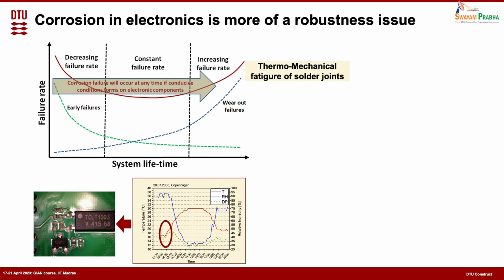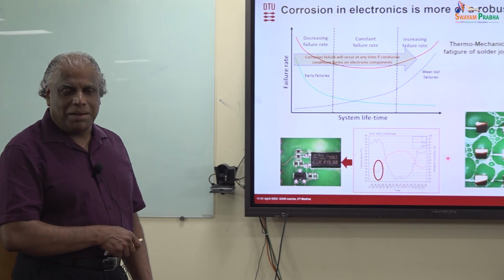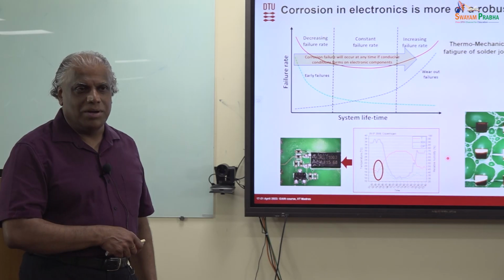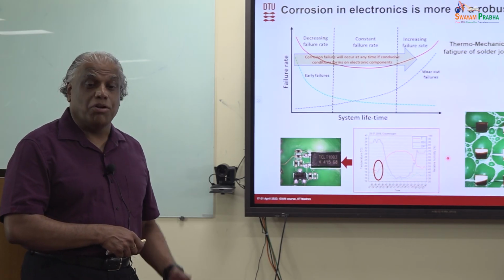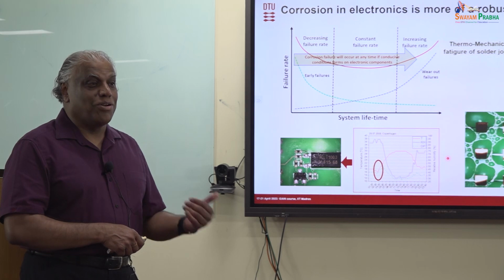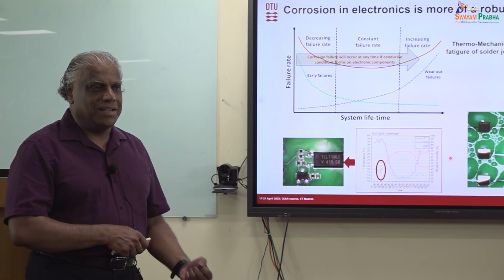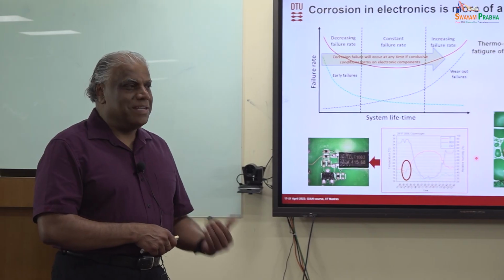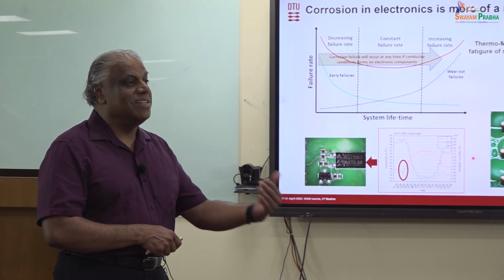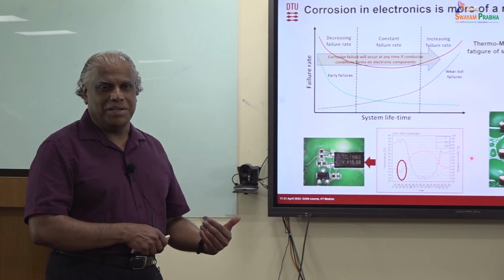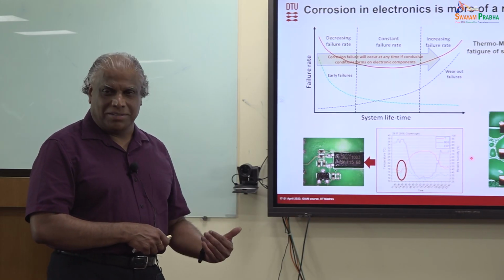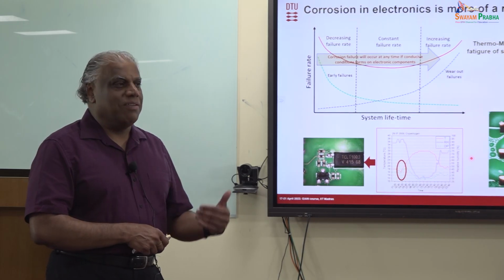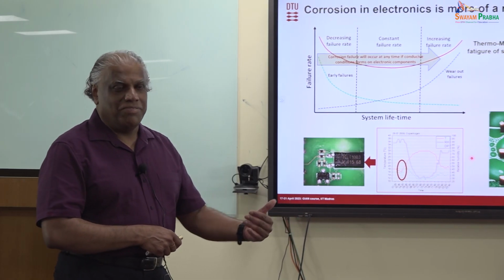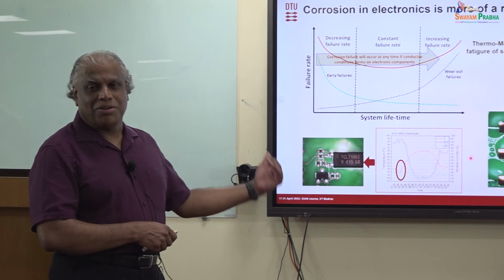So what I mean is that if within a 30 minute period you can get the condensation on the PCB, that is enough to get the failure. That means, in electronics terms, it is not a reliability issue, it's a robustness issue. The system is not robust enough to withstand that condensation for 30 minutes. Reliability means the system has to work reliably for 15 years. Robustness means if you start increasing the stress on a component, what level of stress it can withstand without failure. So this is a robustness issue.